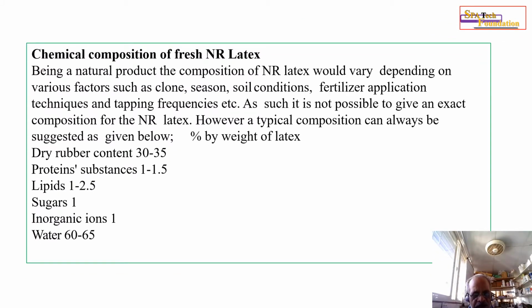The chemical composition of fresh natural rubber latex. Being a natural product, the composition of natural rubber latex would vary depending on various factors such as clone, season, soil conditions, fertilizer application, tapping techniques, tapping frequencies, etc. As such, it is not possible to give an exact composition for the natural rubber latex. However, a typical composition can always be suggested as given below. It is given in terms of percentage by weight of liquid latex. Dry rubber content generally 30 to 35%, protein substances 1 to 1.5, lipids 1 to 2.5, sugar 1%, inorganic ions 1%, water around 60 to 65%.